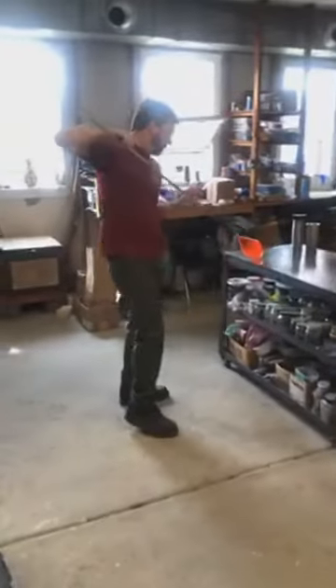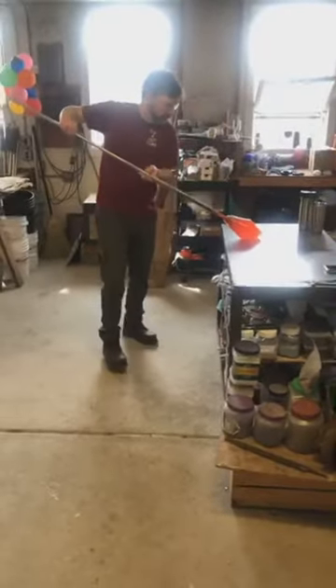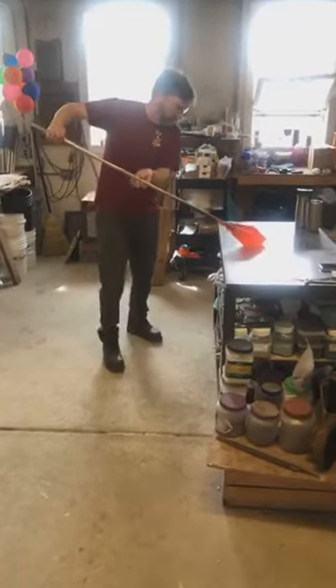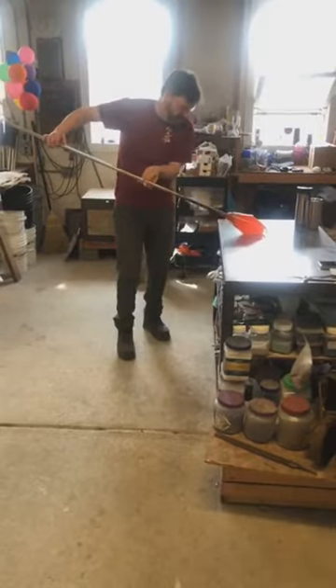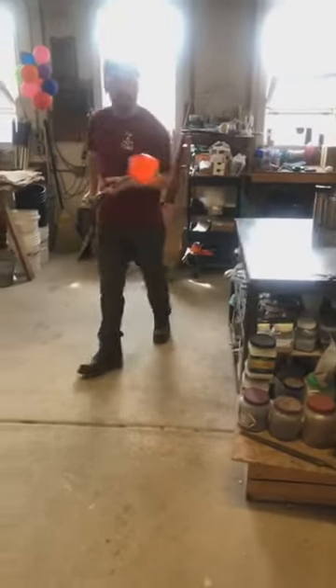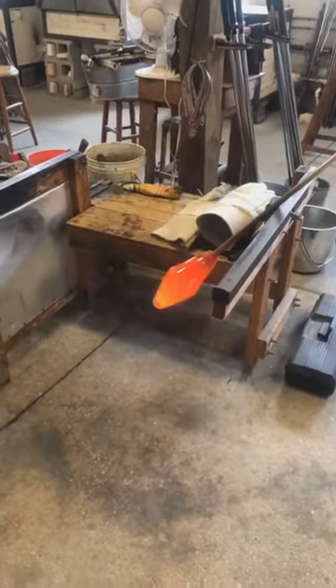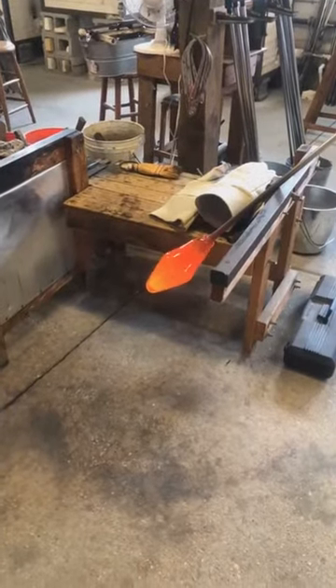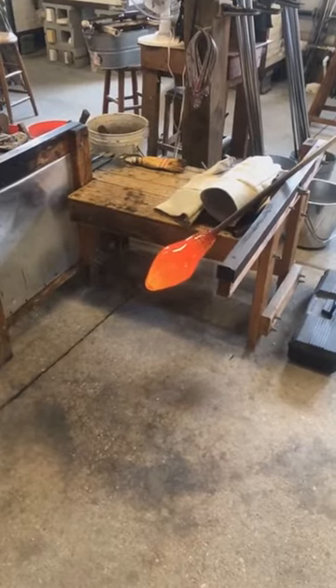Let's go watch Todd with some more shaping here. A lot of what he's doing, you've seen in other pieces, but done much more quickly, only because they didn't involve this much glass. They didn't have that big roll of Murrine, and they had to be put together. So at the Marver, he exclusively cooled the outer end. Now when he blows, you'll see the inflation above that midline. The lower part is not going to substantially increase in diameter. That's because he cooled it.